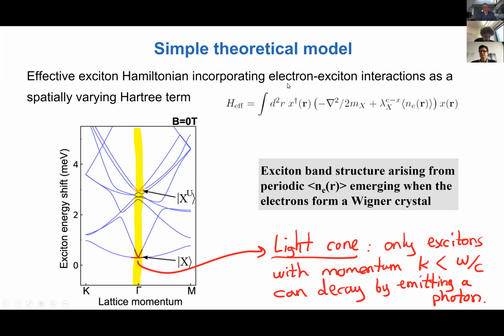We basically, or what Clement said, is that let's neglect the dynamical degrees of freedom of electrons. Let's assume that electrons have a certain density distribution. We neglect the fluctuations, and then it's a density-density interaction. So basically, there is a sort of a Hartree term, an effective periodic potential, leading to a modification of the exciton energy. And this results in the band structure shown here.